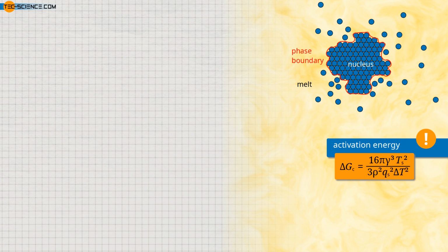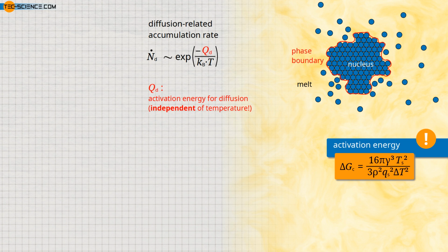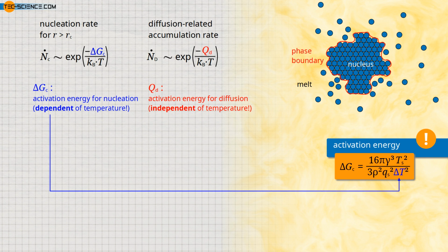The diffusion-related accumulation of particles per time can be described by the so-called Arrhenius equation, which assumes an exponential dependence on temperature. In this equation, Qd is the temperature-independent activation energy for the diffusion process and Kb is the Boltzmann constant. At the same time, it must be taken into account that the nuclei capable of growth must also reach the critical nucleus radius. This can also be described with the Arrhenius equation. The number of growthable nuclei formed per unit time can thus be determined analogously to the previous formula. Delta Gc denotes the temperature-dependent activation energy for nucleation.